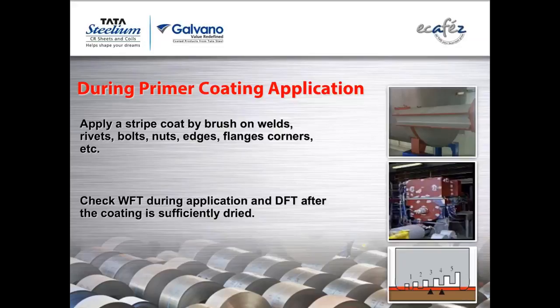Now if I have 60% volume solids, in this case my third tooth is touching the coating, the fourth is not touching, the fifth is not touching. When I look at it from this angle, I come to know that up to this much the paint is there. So 3 means 75 microns is getting touched. Now 60% of 75 microns is going to be the dry film of that particular coating when the solvent evaporates, because 60% is the volume solids of that coating. So 60% of 75, something like 40, 42, 45, is going to be your DFT, dry film thickness.